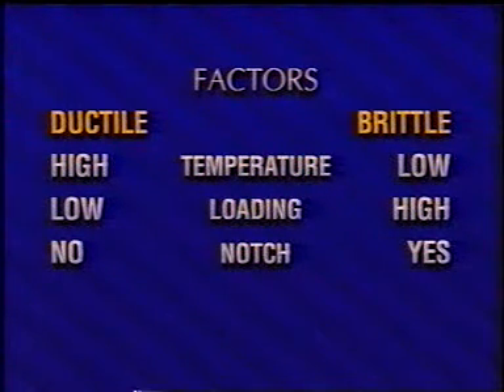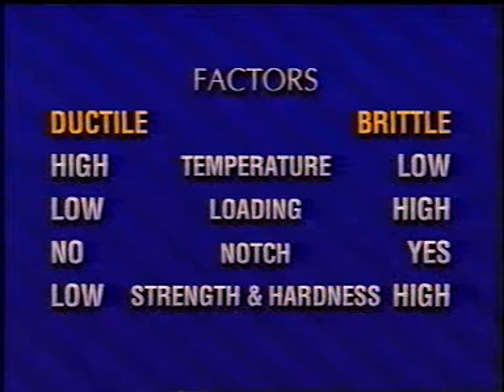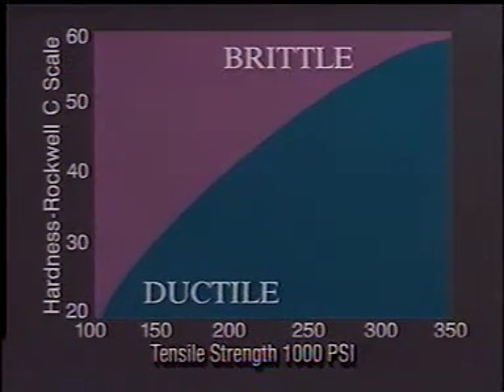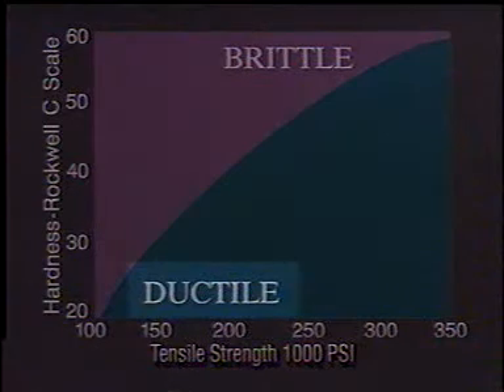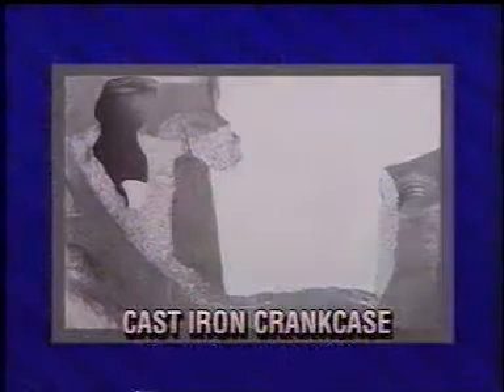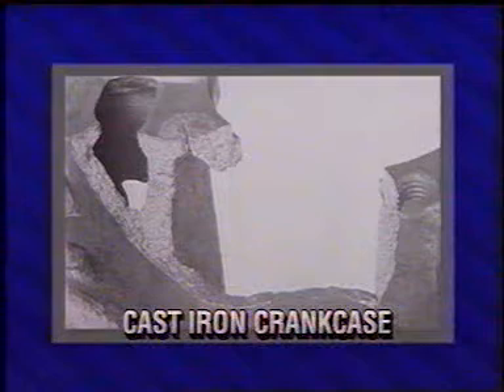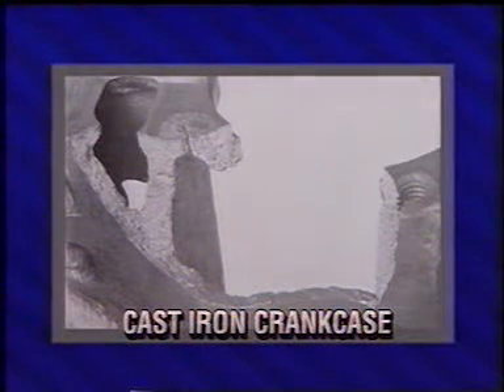When the geometry of the metal is without a notch, ductile behavior is more likely. With a notch, brittle is more likely. Generally, when the tensile strength and hardness of the metal are low, ductility is more likely. When high, brittle behavior is more likely. Sometimes metals do not behave according to the indicators. Gray cast iron, for example, a very common metal, has relatively low strength and hardness, indicating that it should fracture in a ductile manner. But gray cast iron always appears to fracture in a brittle manner. The reason for this strange behavior is the geometry factor. A large number of internal notches are inherent in gray cast iron.